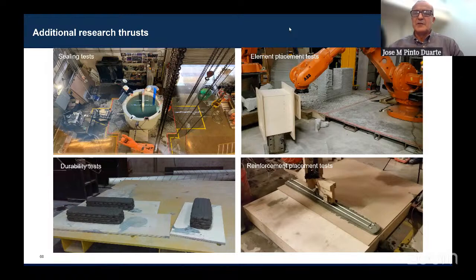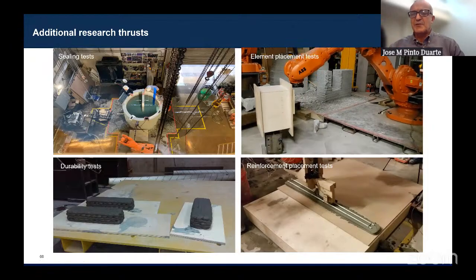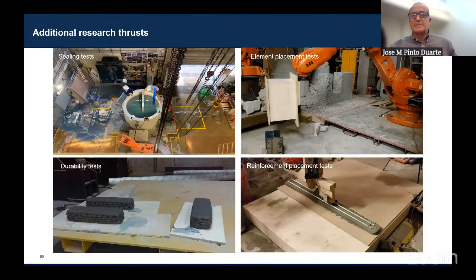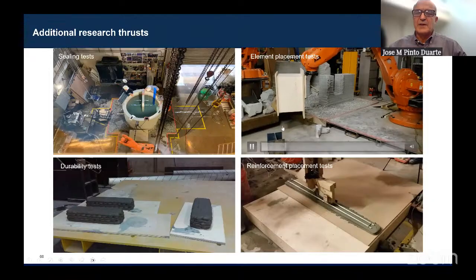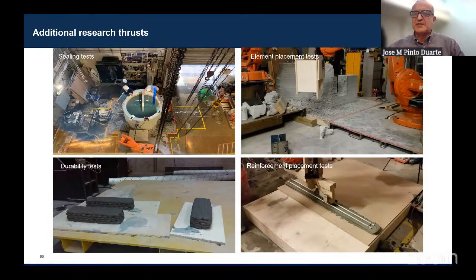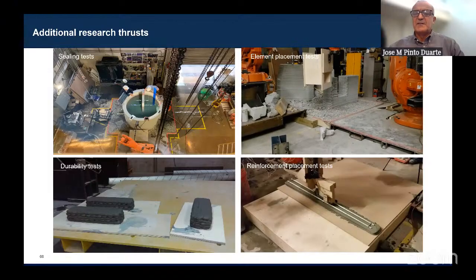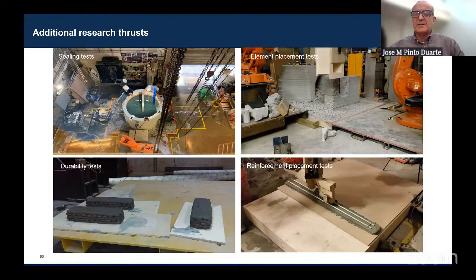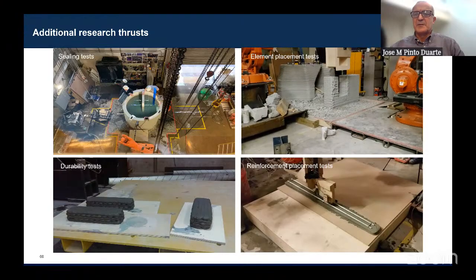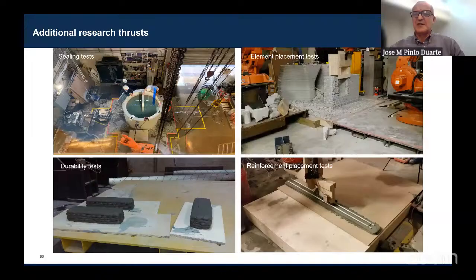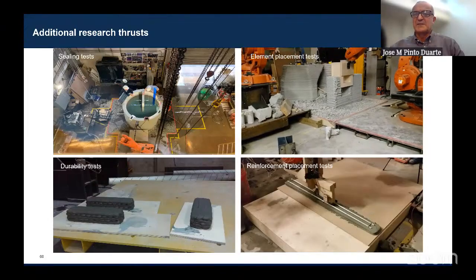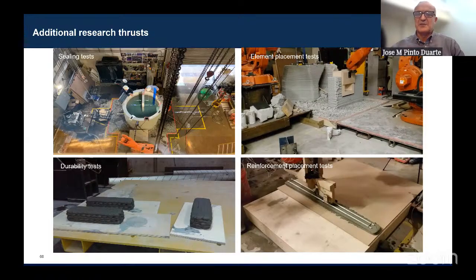And then we are also developing research to automatically place the technical installations, window frames or reinforcement, and so on. So as you can see in this case, a window frame is being placed. These were tests that we did before the NASA competition, in preparation for the finals. And then you can also use the same system to place reinforcement, as you can see in the bottom image. So you'll see the frame will be put in place. This is exactly what did not work at the competition because of the explanation I mentioned before. The pillar deformed too much. So we didn't have the algorithm to compensate for that before.